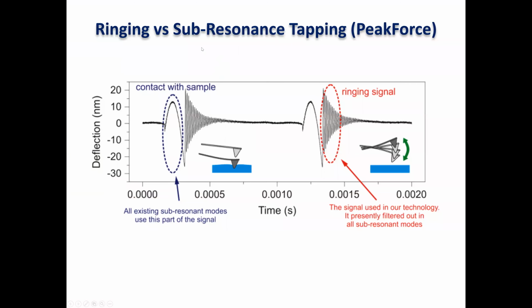So what is ringing mode? Essentially it is an extension of sub-resonance tapping, of which there are multiple versions. It was originally invented by the Russian company NT-MDT, and now there are multiple incarnations of this technique. For example, there is PeakForce by Bruker. We focus on the part of the signal that is typically ignored. In this tapping, the probe goes up and down, touching the surface and developing some adhesion. On the way back, it produces some ringing. No matter what you do, unless you have a really heavily damped cantilever, you have some ringing oscillations, maybe not that many, but at least a few. Typically it is either filtered out or at least ignored. This part of the signal is what we actually use to extract, surprisingly, quite a lot of new channels of information.